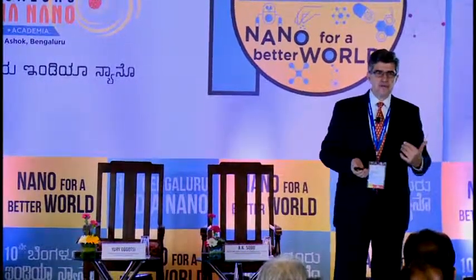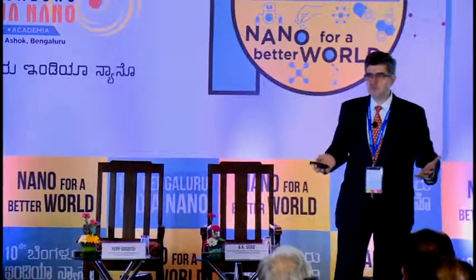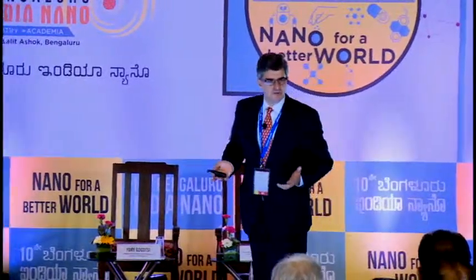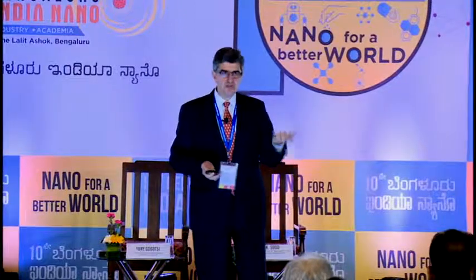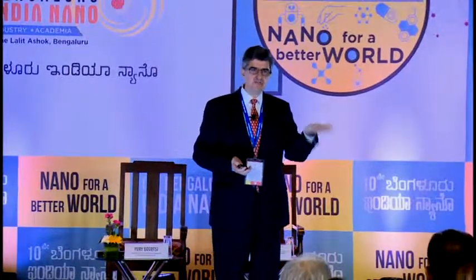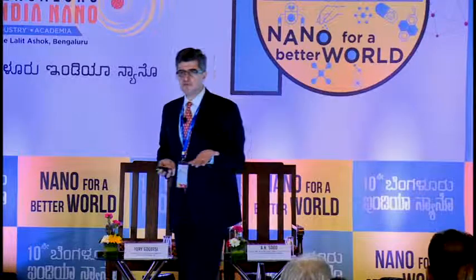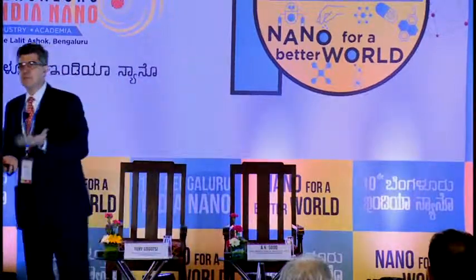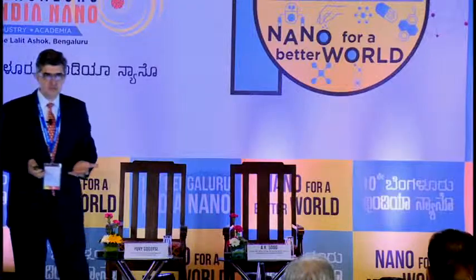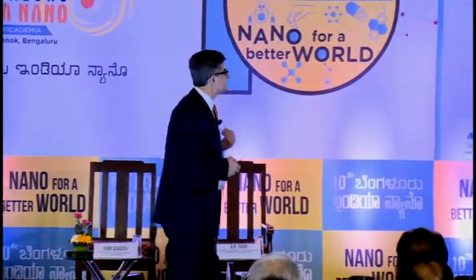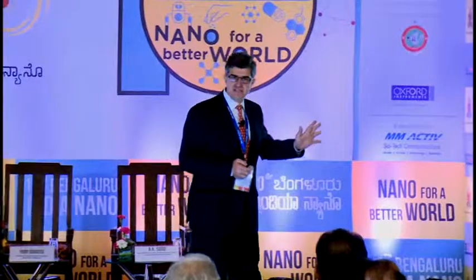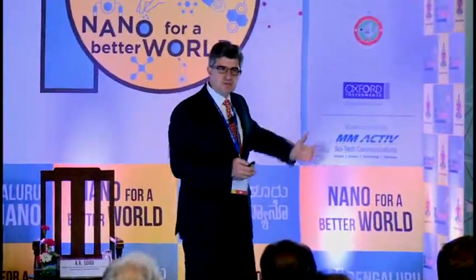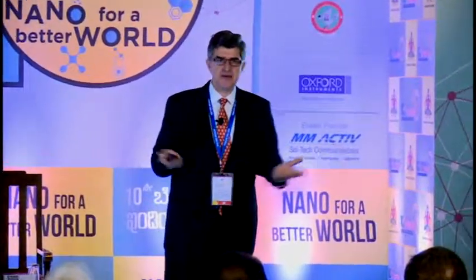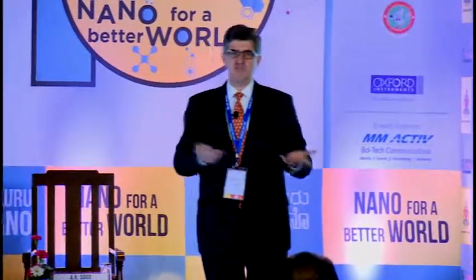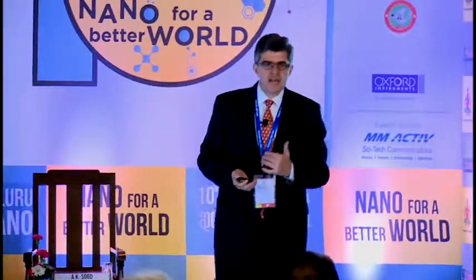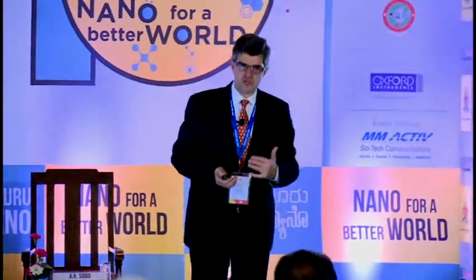Second, you cannot have bulk diffusion, like in current battery materials. You need to eliminate bulk diffusion. So what do you need? You need materials with a high surface area where everything happens on the surface. There are no diffusion limitations. Second, you need a material with much higher conductivity compared to materials used today. And this is exactly where MXenes can open an opportunity. They can actually have properties of a supercapacitor because they're high surface area, two-dimensional sheets, but they have transition metal on the surface that can change oxidation state, storing more energy by redox reactions.